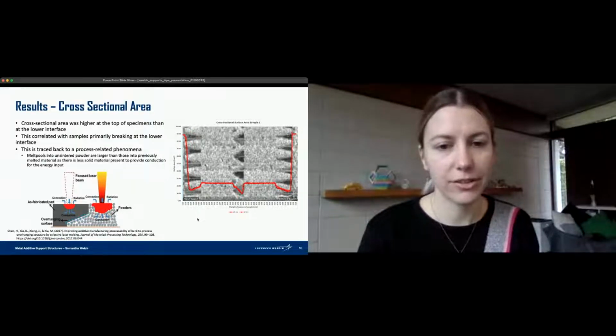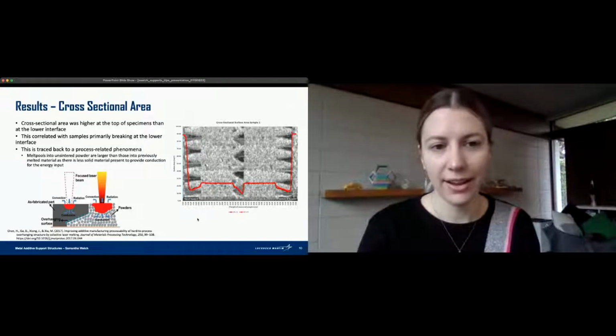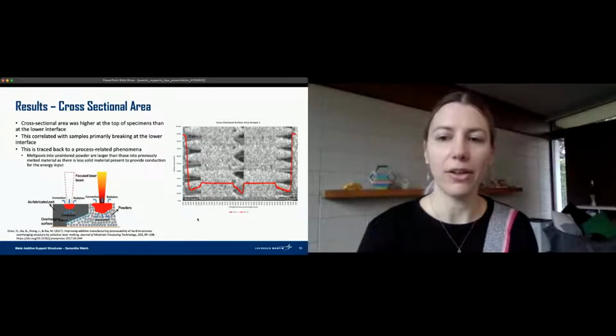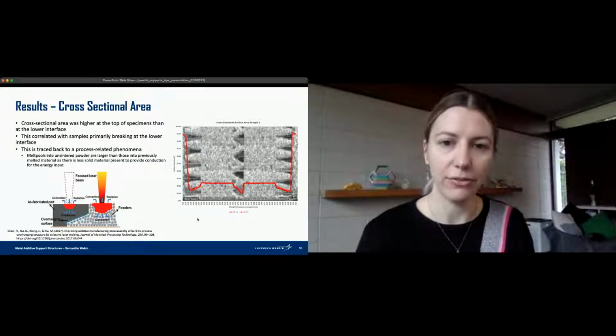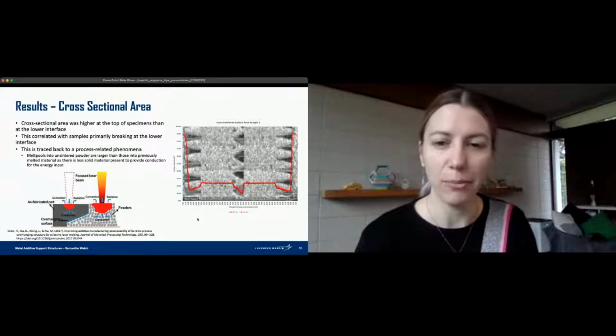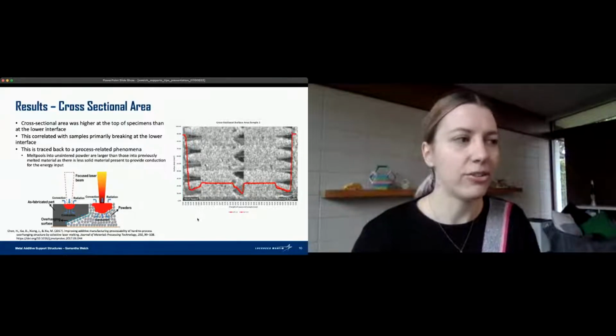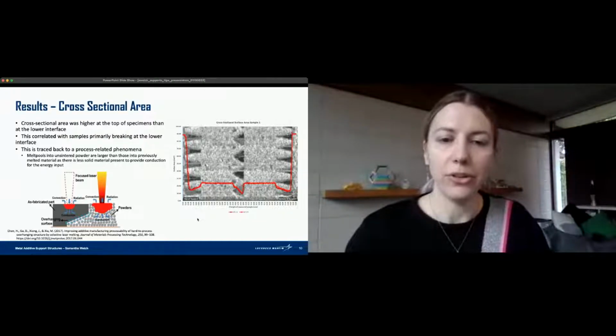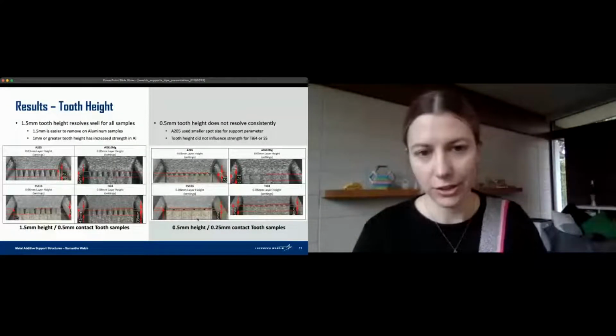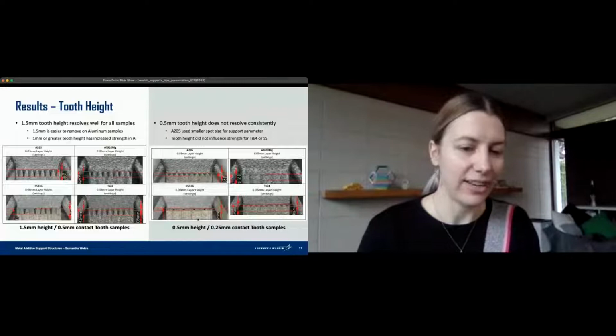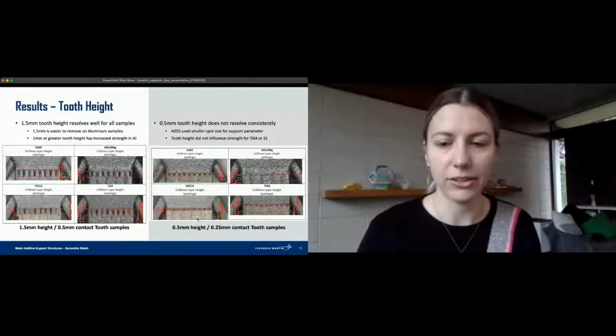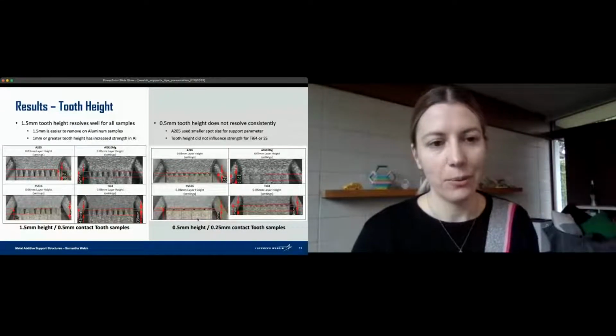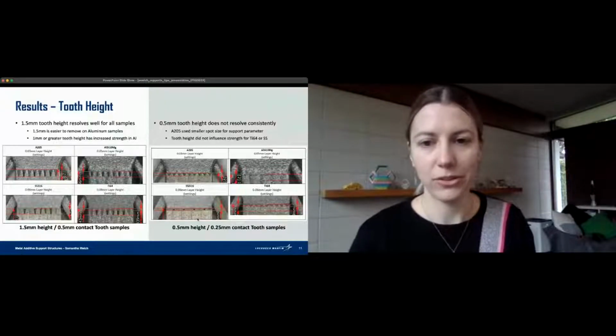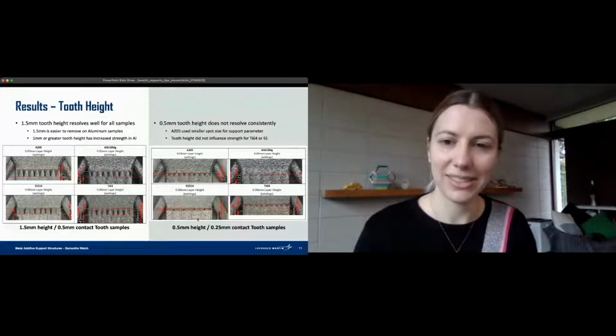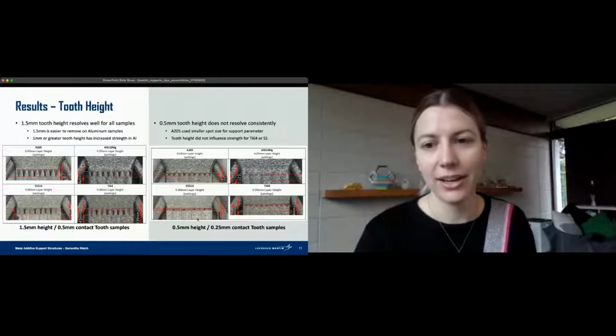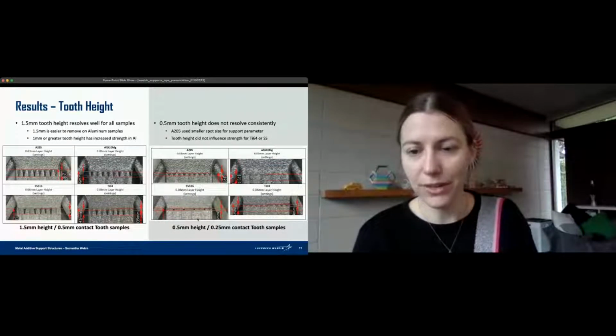The next interesting results I found were of the tooth height. A lot of the papers I was finding, and other recommendations, were recommending fairly small interface regions, 0.5 millimeter tooth sizes. I just really hadn't had luck with those in our applications, and we were using much larger tooth heights. And I had an inkling as to why, and that did actually get chased out in the study. When you're working on smaller platforms with smaller laser powers, smaller spot sizes, and therefore smaller melt pools, you're able to resolve these small features repeatably.